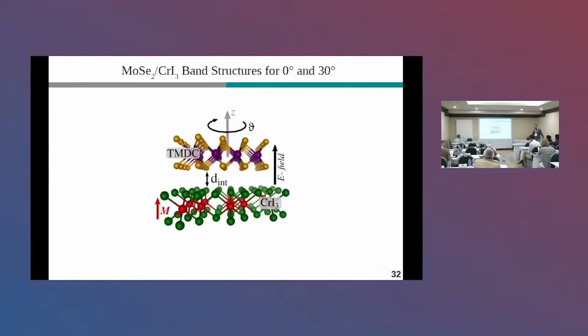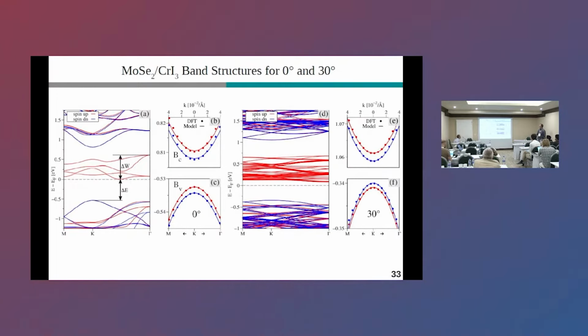And this is of course why we considered this in DFT and checked what the twist angle does, what a gate field does to this, and the story goes like this. So if you start with a 0-degree twist angle structure, you can very nicely recognize the band edges of the TMDC here around the K valleys. These spin polarized in-gap states result from the chromium triiodide, which is also responsible for the quenching of the PL peak for one light helicity.